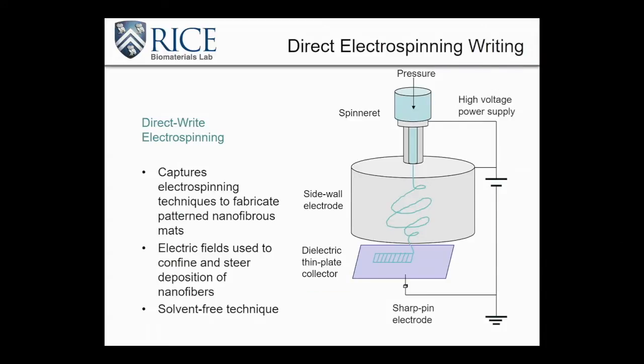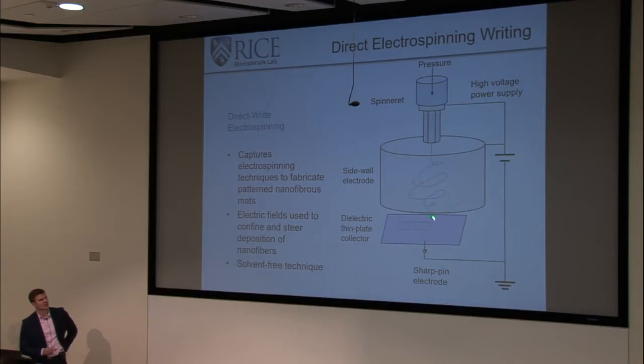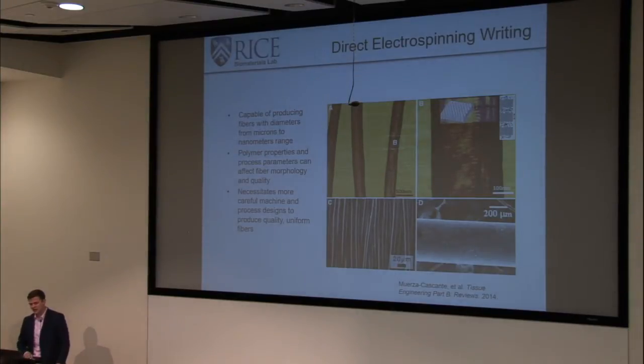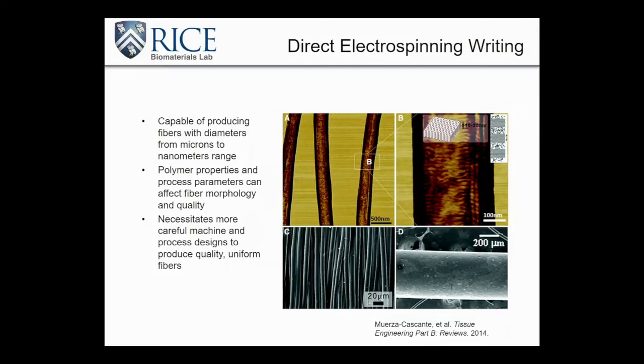So again, what we're focused on doing here is capturing some of those electrospinning techniques to fabricate patterned nanofiber mats. And we're not talking about just deciding the direction of these fiber mats, but we're able to move in the full three-dimensional space here to design scaffolds that are on the nanometer level. This technique drastically improves some of the scaffolds that we see in electrospinning, but it also comes at a cost. So while we're capable of producing those same electrospun fibers at these cellularly relevant levels, it's very easy to introduce defects into the fibers. So you have to use a lot more fine tuning on the voltage difference, the speeds at which the materials are ejected from the spinneret, things like that. And we'll talk about that in a second.